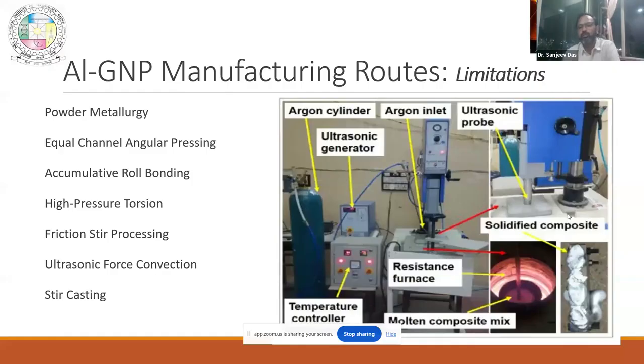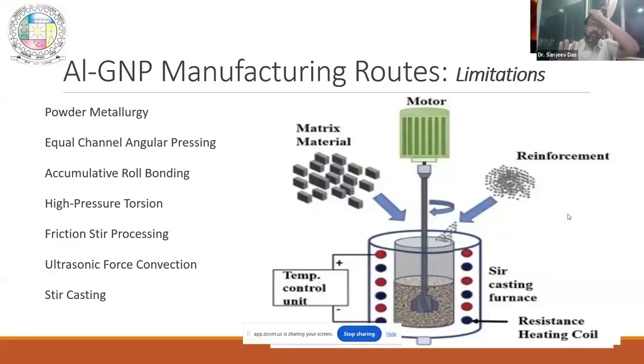The second last one is ultrasonication. Ultrasonication is widely used by a lot of people to make nanocomposites, but ultrasonic forces basically don't incorporate the particles inside the liquid metal. What it does is uniformly mix them, but you have to incorporate them by the stir casting process, and then you will use the ultrasonic process to uniformly distribute these nanoparticles inside the metal. So ultimately you have to do the stir casting process.